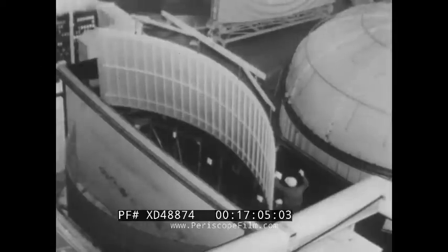Shaping the tank skin panel assemblies is done by brake forming. The panel moves slowly through the power brake dies. Deformation is pre-calculated to produce the final 16 1/2 foot radius for the panel. After inspection, the surfaces are cleaned and prepared.